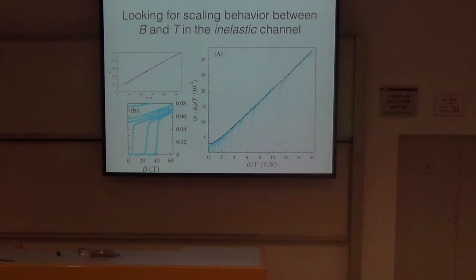So rho naught that you're subtracting is field dependent? This is very good. It is absolutely not field dependent. It's not? No, absolutely not. So this is a good point. This is the last time that you will see an offset like this, just to make sure that you know that we haven't fudged any data. Rho naught is the intercept from the T-linear part of the resistivity. So the basic idea is to subtract this elastic part of the resistance, so you are only looking at the temperature or field-dependent part of the resistance. And so that's the part.